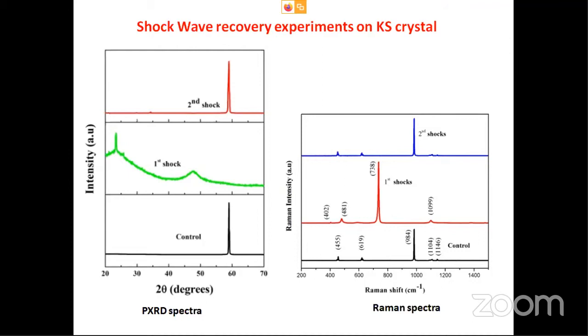This is another interesting crystal. This is the XRD of a single crystal. It's a single unidirectionally grown crystal. It is giving only one peak for the diffraction. After giving the first shock, the XRD completely becomes like this. And after the second shock, it becomes the old one. Actually, the phase is transforming from one phase to another phase.